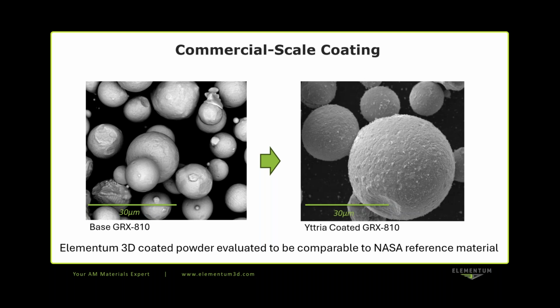So as I mentioned, we looked at 5 different commercial scale coating methods and settled on one that's working very well. You can see on the left image the base GRX 810 alloy, and on the right image that's the yttria coated alloy. And we found that our commercial scale coating method produces results that are very comparable to the NASA reference material.